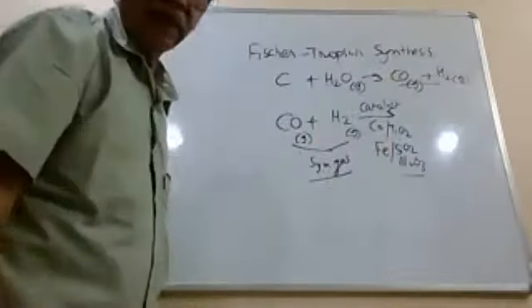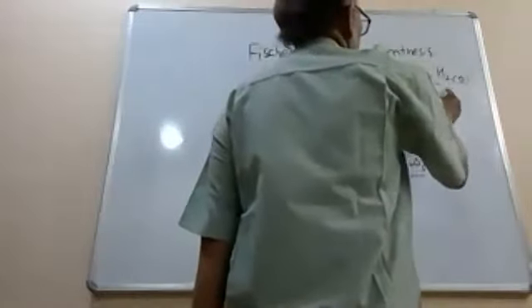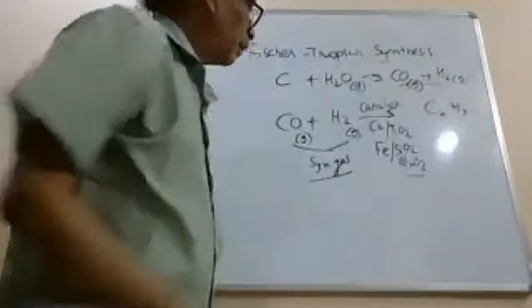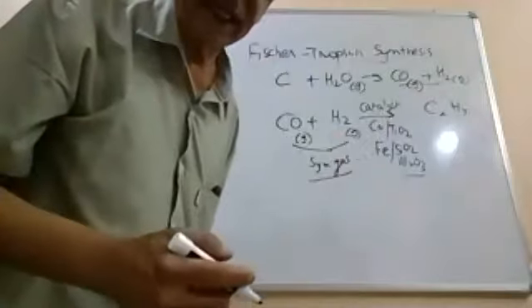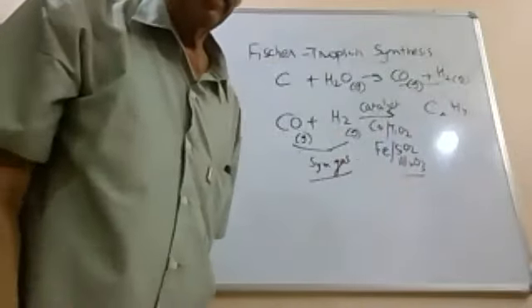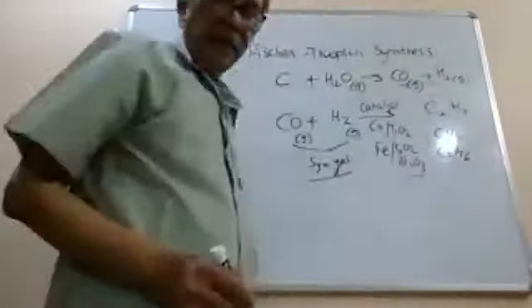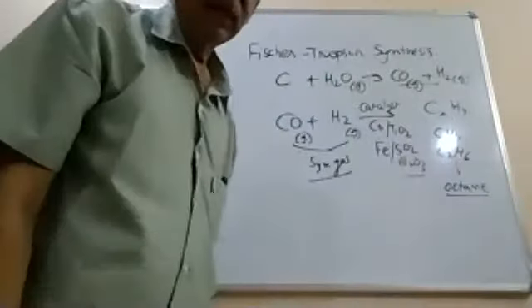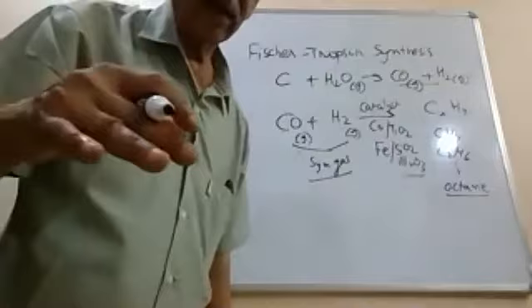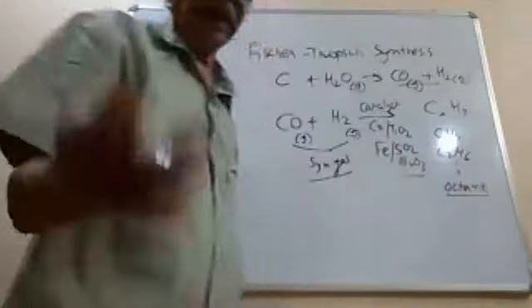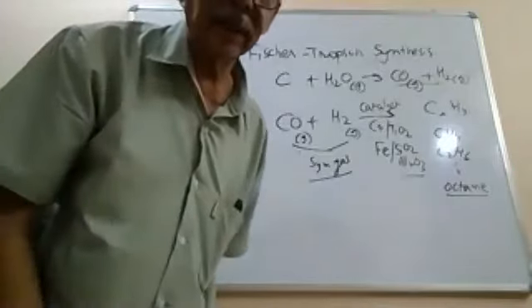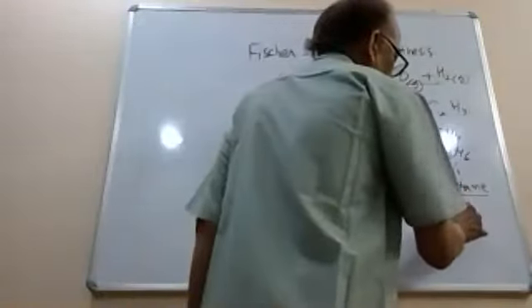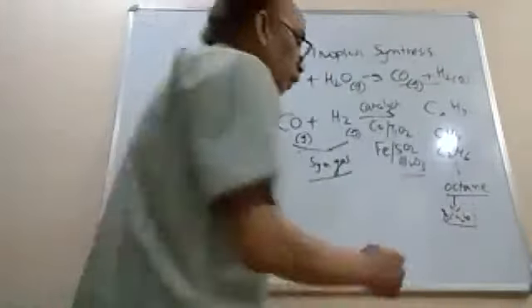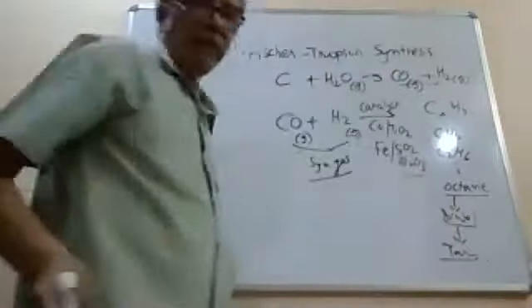And when you pass the syngas over the catalyst, you get a variety of hydrocarbons. By changing the conditions, the temperature and the pressure of the gases, you can make anywhere between methane, ethane, and all the way to octane. Most of the Fischer-Tropsch processes give you linear chain hydrocarbons, and you can do isomerization on the octane to get isooctane, which is what gasoline is. By changing the conditions, you can also make diesel. And you can also make tar, all kinds of petroleum chemicals.